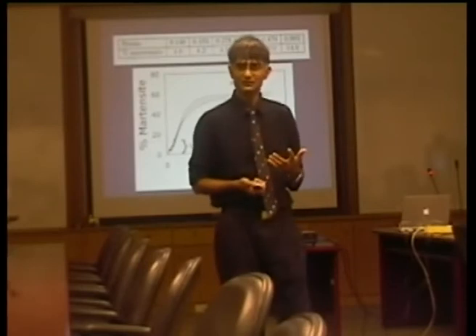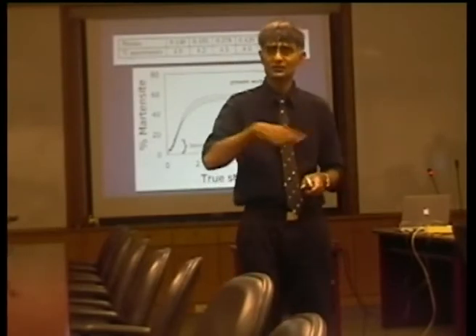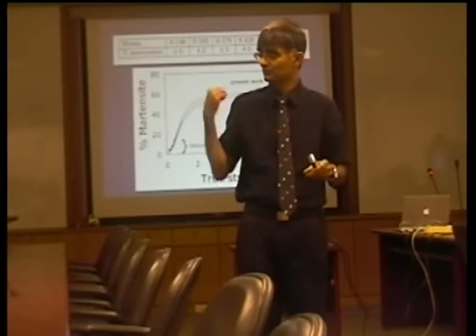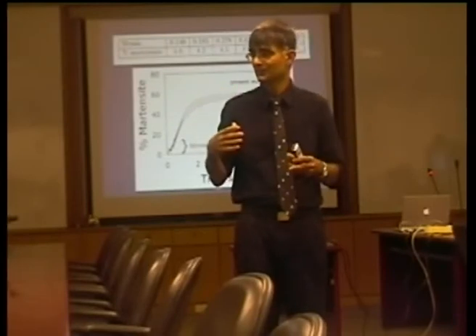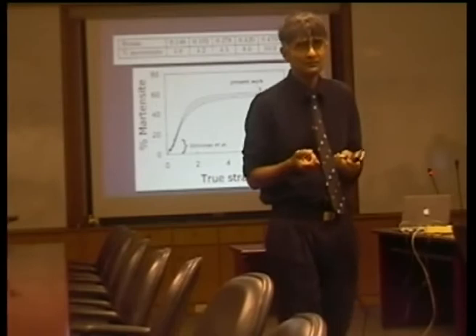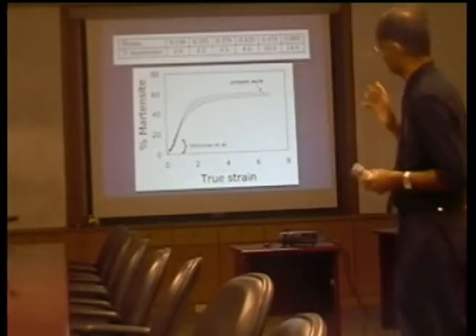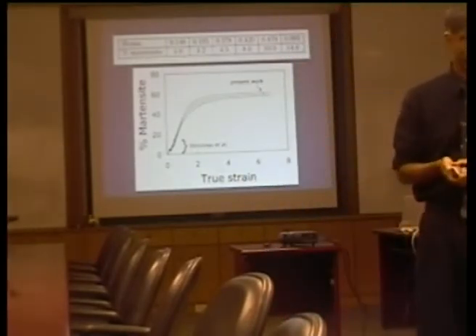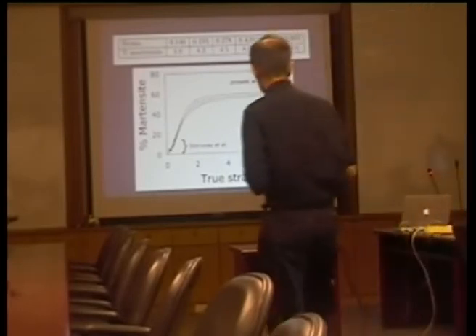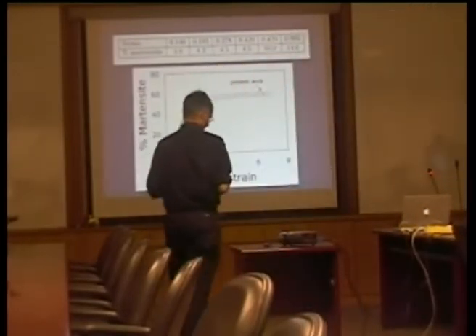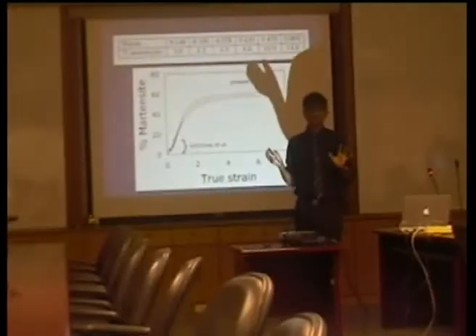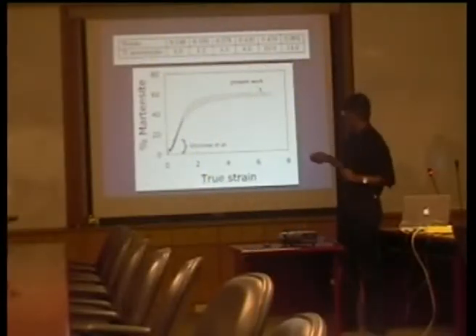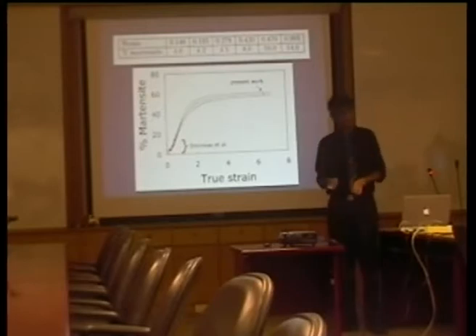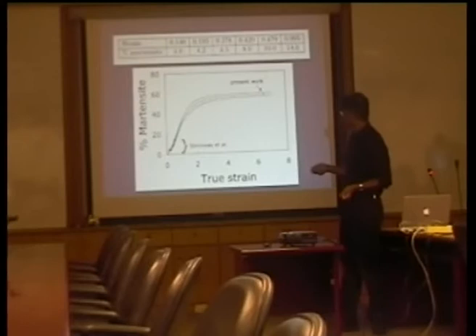Well, the first thing we did was we didn't want to draw any lines by ourselves on all those data put together. We want a mathematical method which will automatically identify what the relationship should look like. And that method is called neural network analysis. So we didn't bias the method in any way. And if I take these data and this data point and present it to a neural network, it produces this curve. And that curve is very exciting.